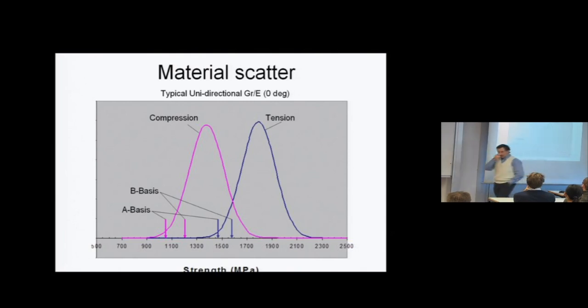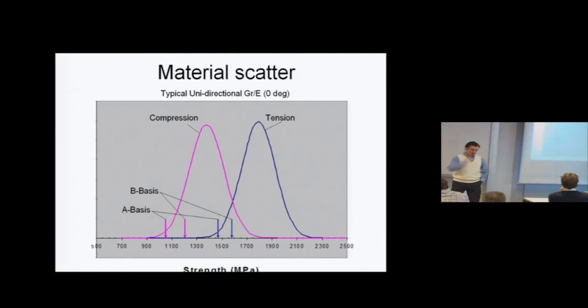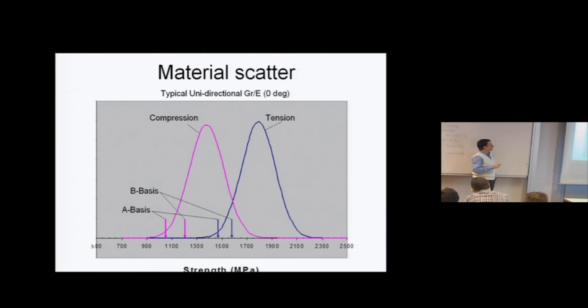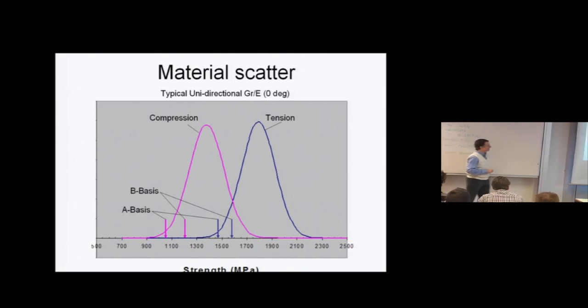So if you take all these, if you take material scatter alone first, then, for example, this is typical tension strength data. And this is the strength in megapascal shown on the x-axis. Then the distribution of the tension strength is here. And for the exact same material, the distribution of the compression strength is here. Typically, compression is slightly less or significantly less than the tension.